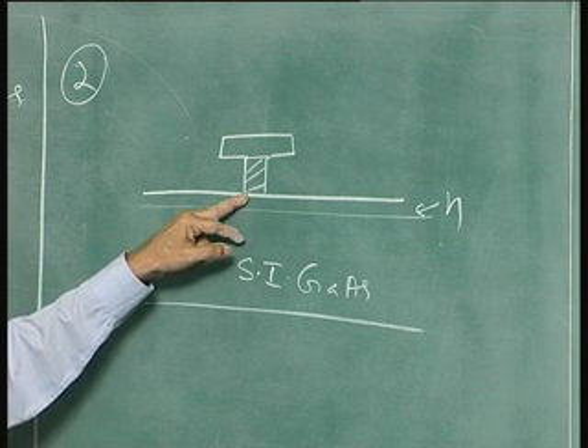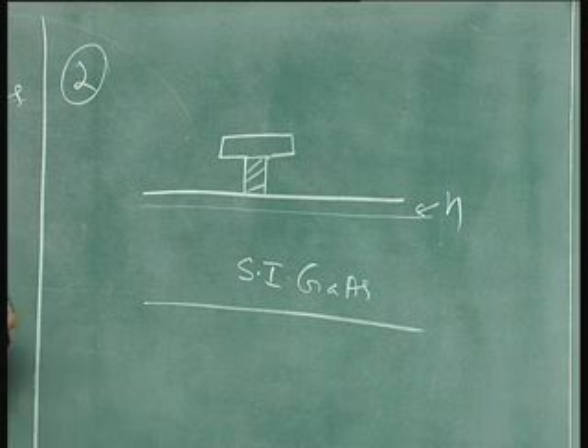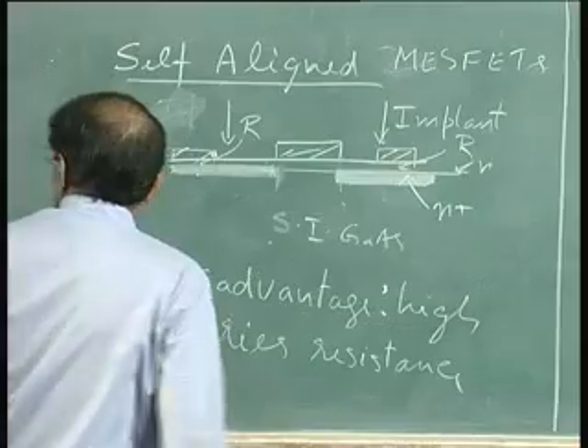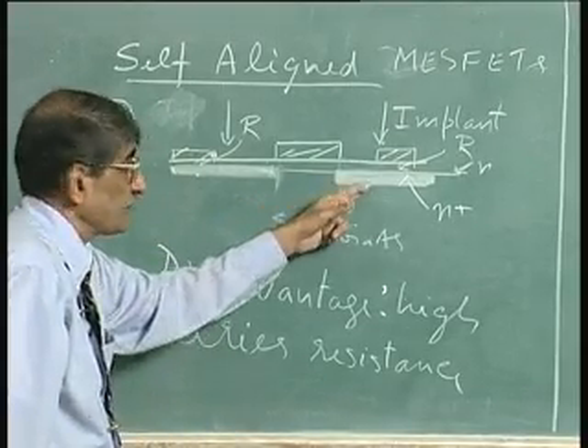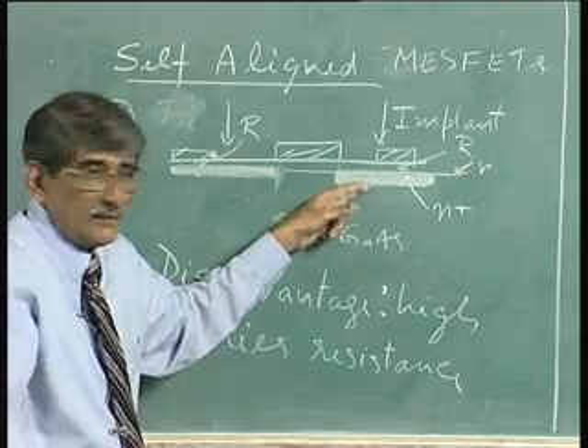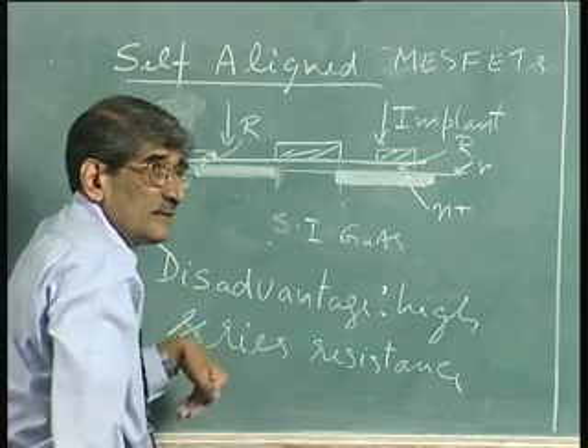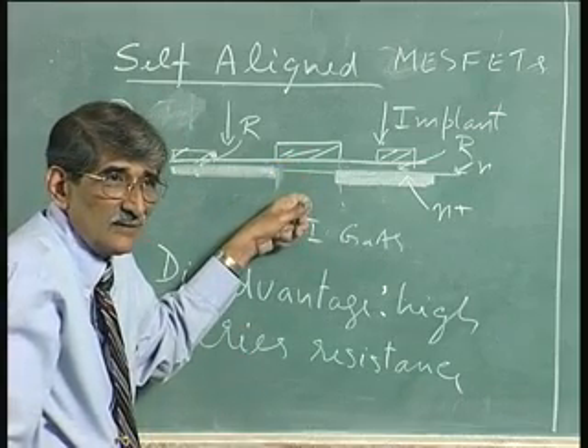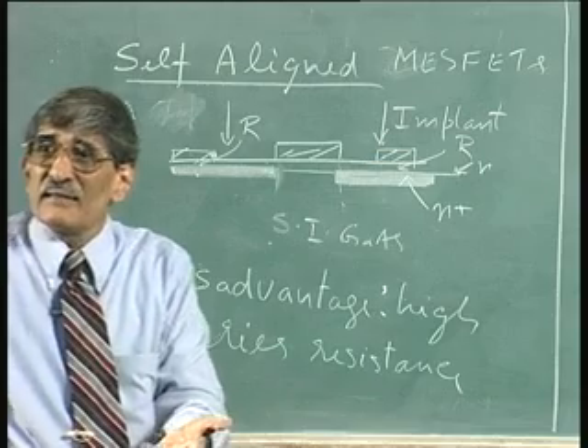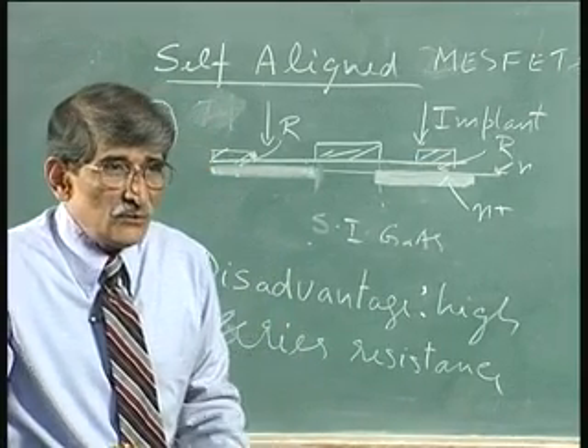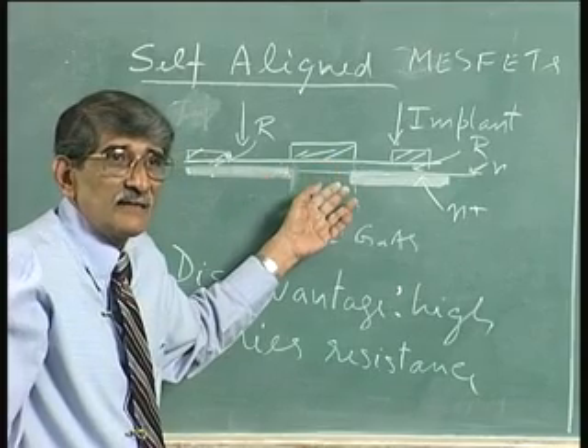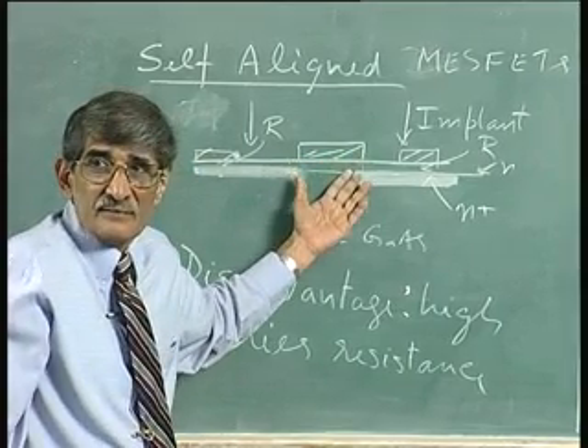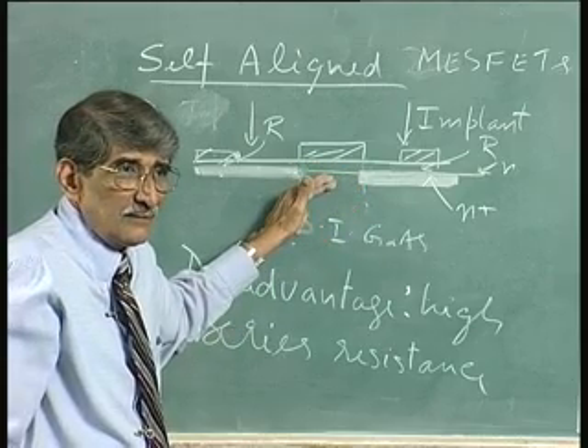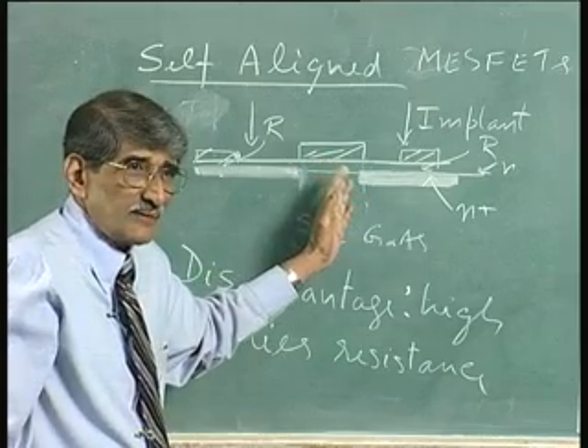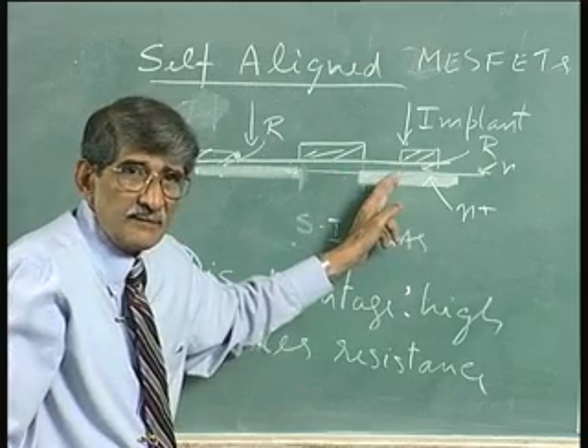Okay. Of course, even there also that sort of problem is there, in the sense after the implantation, let me come back to this, after the implantation of this, you must subject it to annealing. If I use this gate as the mask for implantation, the gate is in contact with the substrate, you must anneal it at 700, 800 degree centigrade to recover the damage. You can't afford to have a metal which is reactive with the gallium arsenide. So, you must put refractory metals here like tungsten as a metal gate. Okay. It would work out all right, but the problem here is series resistance.